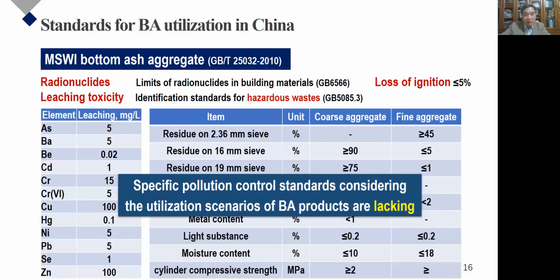For bottom ash aggregate, a specific standard was issued in the year 2010, in which the limits of radionuclide, loss of ignition, leaching toxicity of heavy metals were proposed. Besides the technical specifications for the coarse and fine aggregate from bottom ash, such as the size grading, contents of metals, light substances, moisture, and compressive strength, the leaching toxicity is referring to the identification standards for hazardous waste, which is less stringent compared with recommended values for cement as listed in the last slide.